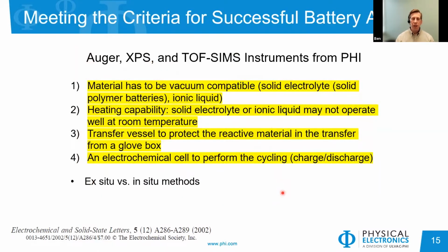So if we want to perform successful battery analysis using these type of vacuum techniques, Auger, XPS, TOF-SIMS, there are a few criteria that we would try to meet. So the material does need to be vacuum compatible. For some of the newer solid electrolytes or ionic liquids, that's not so much a problem. If you are using liquid electrolytes, you would likely need to wash that from the circuit after you've done your testing before you put it in the instrument. We'd like to have some kind of heating capability built into the instrument because some of the operational conditions are not always just at room temperature. So we'd like to simulate that and watch this happening somewhat in situ in the system.